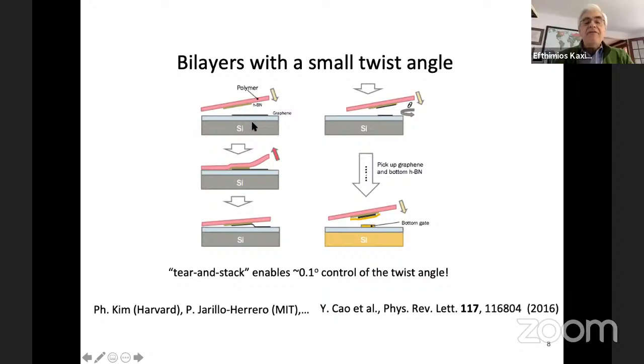So they have a graphene layer, let's say. So this is this thin black line here. And they stick on it another layer. This is the hexagonal boron nitride. And then they pull up the hexagonal boron nitride and they rip the graphene layer apart in the middle. But by doing so, they now know the original orientation of the two parts. So they can bring one part on top of the other at a relative twist angle, and they can control this twist angle down to less than a tenth of a degree, which is really quite impressive.